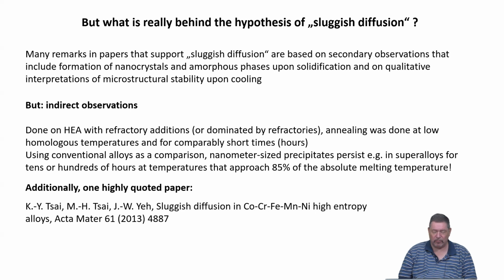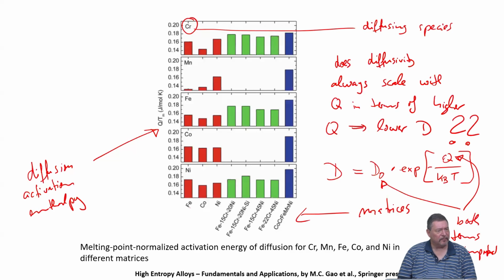And this is because the prefactor is also important, this D naught, because that's a function of probability of doing the jump, how many alternative and analogous direction of the jump is there, how probable is the back jump with respect to the forward jump, and how often is it attempted per second. This all goes into this prefactor, and this is sometimes the ruling factor.